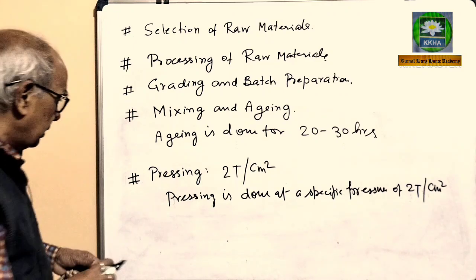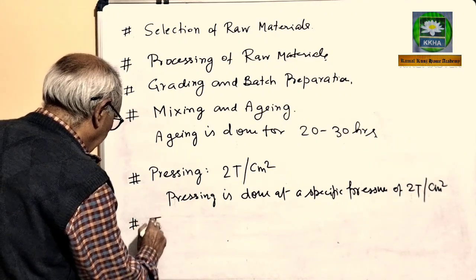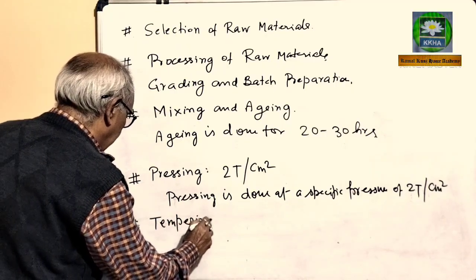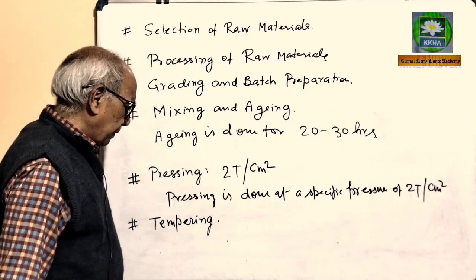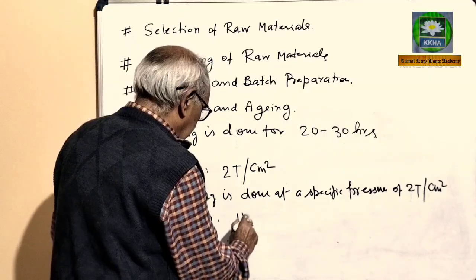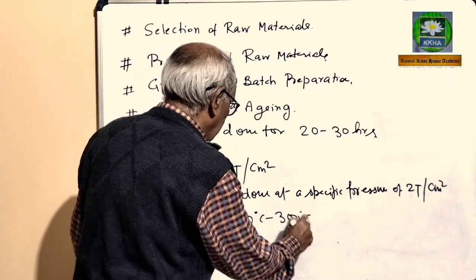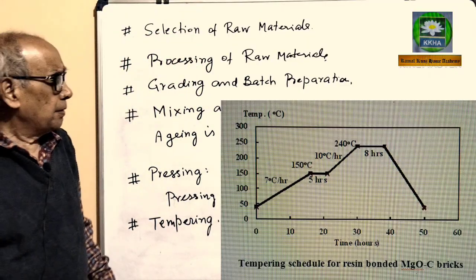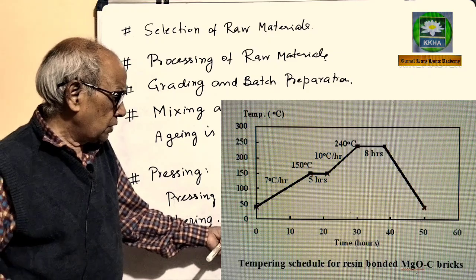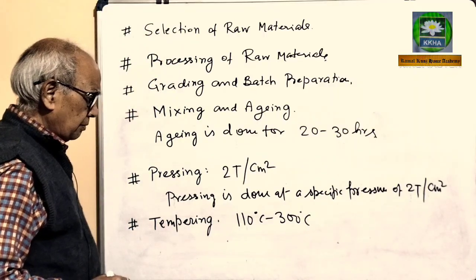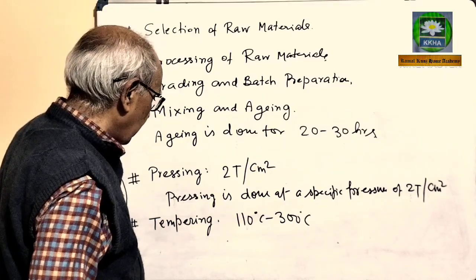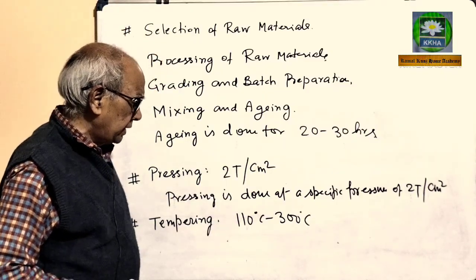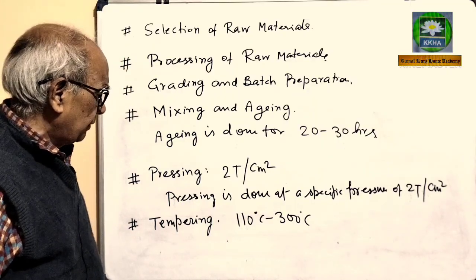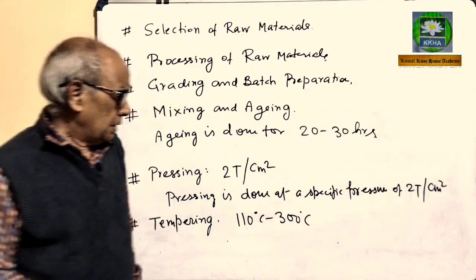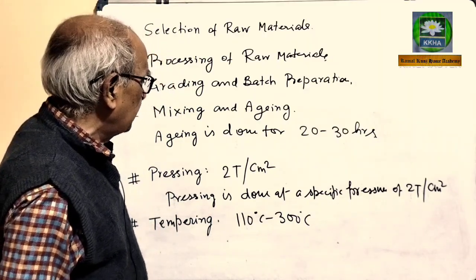So next step is tempering. Tempering is carried out at temperatures 110 degrees Celsius to 300 degrees Celsius. Tempering schedule is shown here in the photograph. Initial heating rate should be slow so that surface does not get hardened. Otherwise it will create problem for removal of volatile matter and moisture. So initial heating should be slow as shown in the heating schedule diagram. And after tempering, inspection and testing is done.